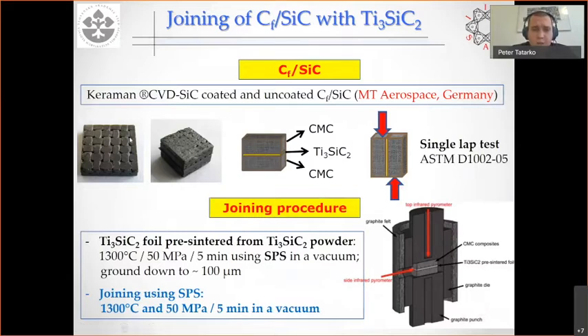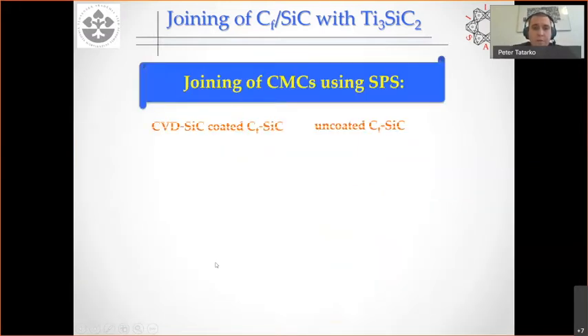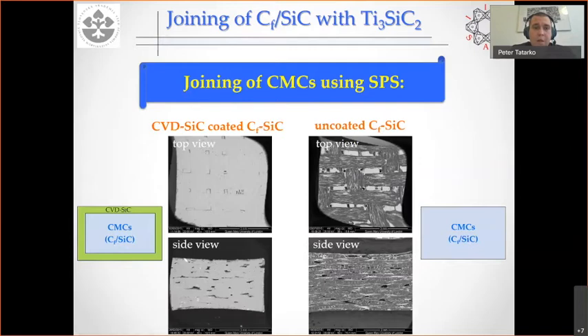Here, as I mentioned, we got some samples from MT Aerospace from Germany, and then we used a very similar process as I described before. Just in this case, we used carbon fiber reinforced silicon carbide, and we used the same temperature and all the same parameters like we used before. Just to remind you that we have two types of material. One was coated: you see here, it was fully coated from all sides by a CVD silicon carbide layer, as I explained before. And here you see the uncoated sample.